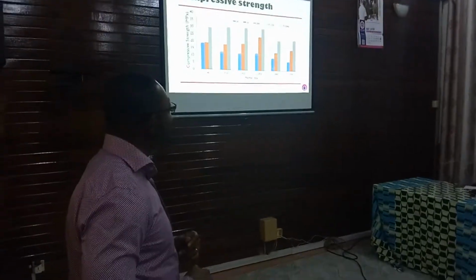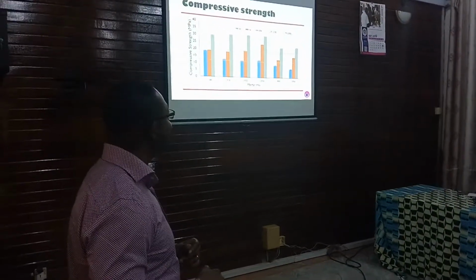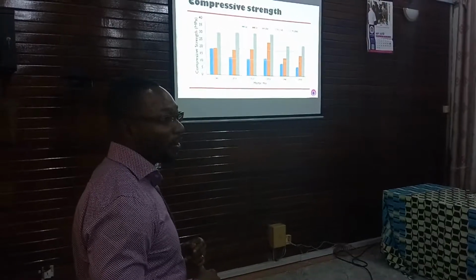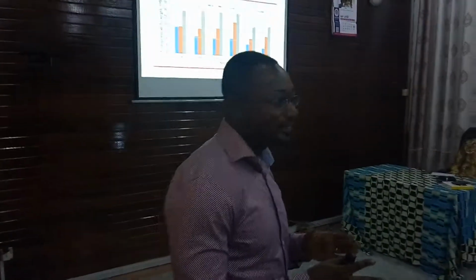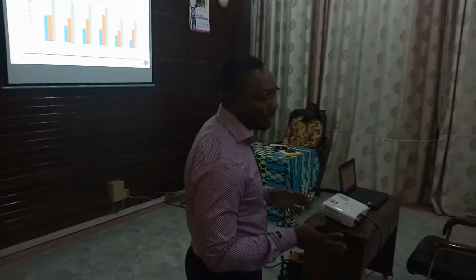Go over this again. The yellow line is the minimum standard for masonry cement at 7 days, which is 12.4. And then the green line is the minimum strength at 28 days for masonry cement, which is 20 megapascals. But then you realize that you are achieving higher strength at 7 days, even at 40%, and the same at 28 days. Though it is lower than the control, but who cares? I'm balancing economics against performance.